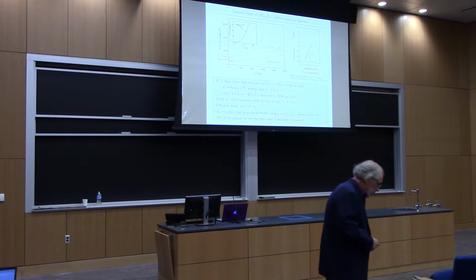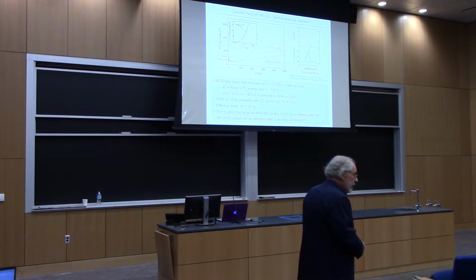Effective mass is about 25 times the electron mass estimated from specific heat. The entropy is much too large for antiferromagnetism with this small moment, which gave rise to the exclamation that that isn't the order that's going on. And so since we don't know what it is, the term hidden order was coined. And so as I said, this order parameter, even though a lot of progress has been made, has not been definitively identified after 3 decades of research.